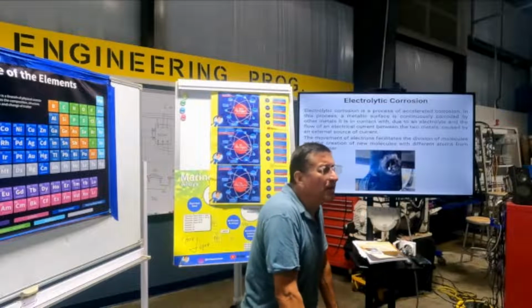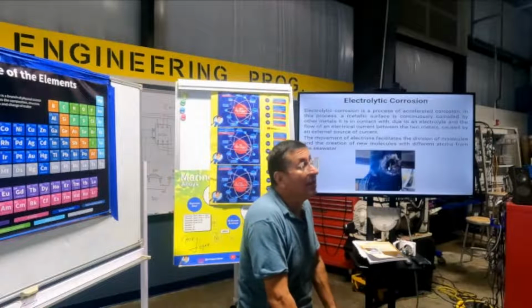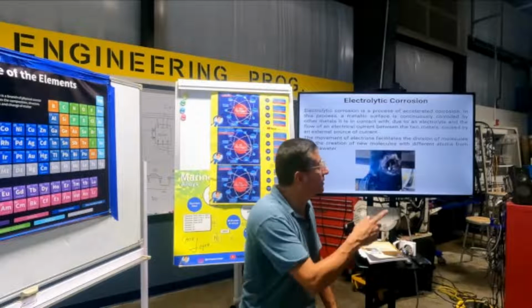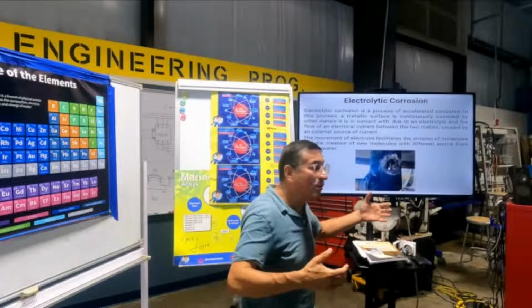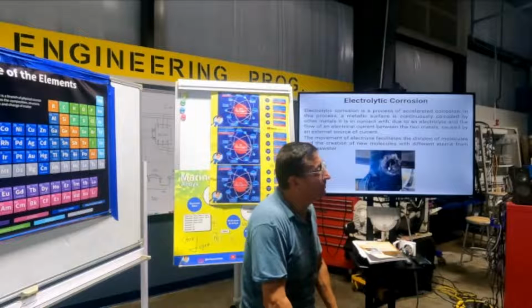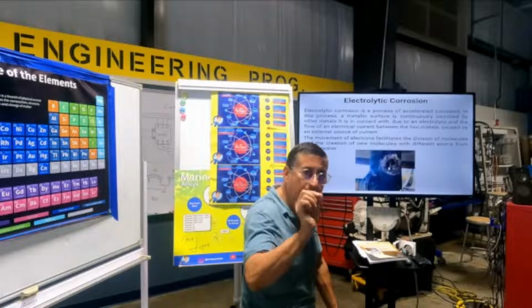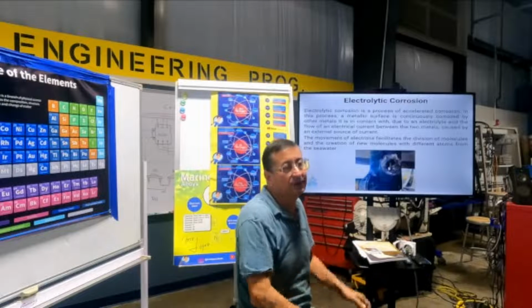A couple of months later, fuel leaks in both tanks. Why? Because those tanks were the fuel tanks of a big truck. This is not marine grade aluminum. It's industrial aluminum, and of course it fractured, cracked, and leaked fuel. It should be marine grade aluminum, Series 5000.